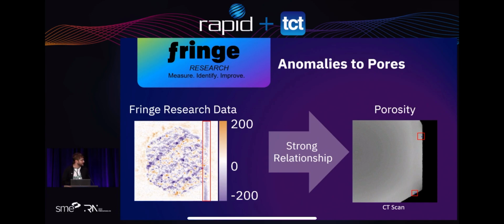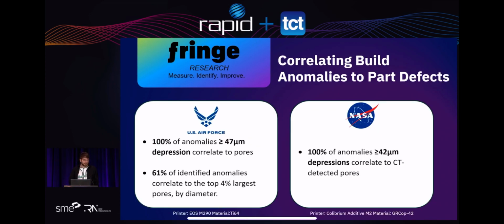And so I didn't want to get too technical into all the studies, but we have some major milestones to report from some pretty big contracts that we've been working on for several years with the US Air Force and NASA. So the US Air Force, they have thousands of parts on back order. They want to print them. They can print them. The parts look good, but they need a way to prove that the parts are high quality. And so we did this study where we put a challenging geometry part and then a bunch of dog bones into the build. There was recoater streaks, recoater hops, spatter, short feeds that impacted our nice parts based on a challenging geometry. And what we found was 100% of the anomalies that we measured in the powder layers, hops and streaks, short feeds, they created pores automatically detected using a CT scan on a dog bone specimen.